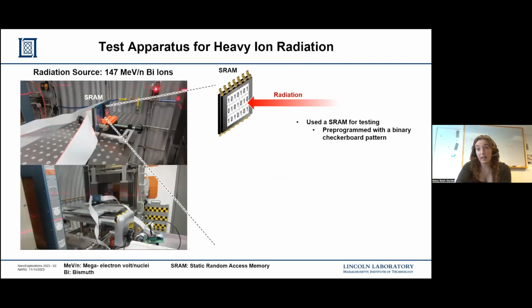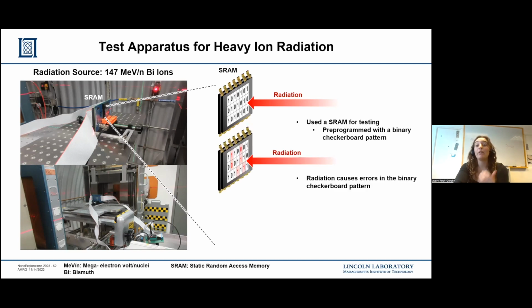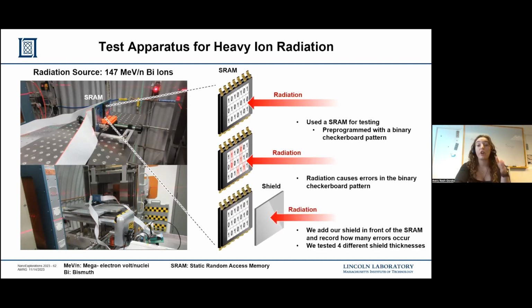Moving on, we wanted to test the heavy ion dose and how that affected the electronics. So heavy ion radiation causes single event effects. Single event effects are super specific to whatever electronic they're hitting. So unlike gamma radiation, where we used a detector, we opted to use an SRAM that we pre-programmed with a binary checkerboard pattern. We hit the SRAM with radiation, and we recorded the amount of errors that were caused. We then repeated this study with our shields in front of it, and we recorded how many errors the SRAM caused with the shield in front of it.